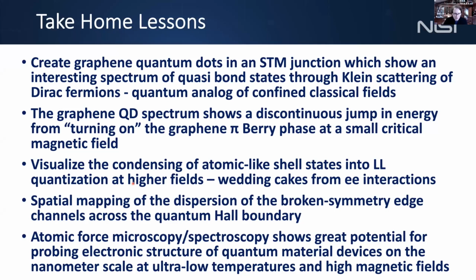at ultra low temperatures. We looked at how we can measure the energies of the broken symmetry states and map them across the quantum Hall boundary. And I think the AFM has a lot of potential for future measurements at ultra low temperatures and high magnetic fields. So thank you for your attention.